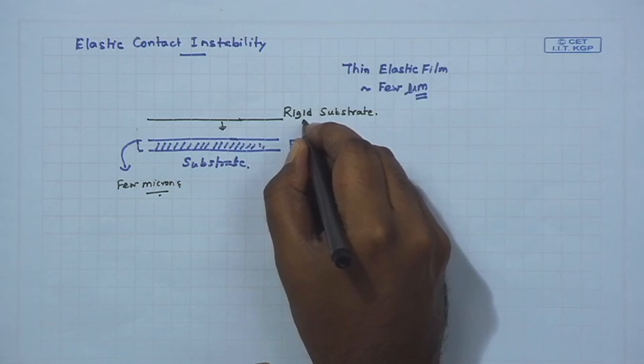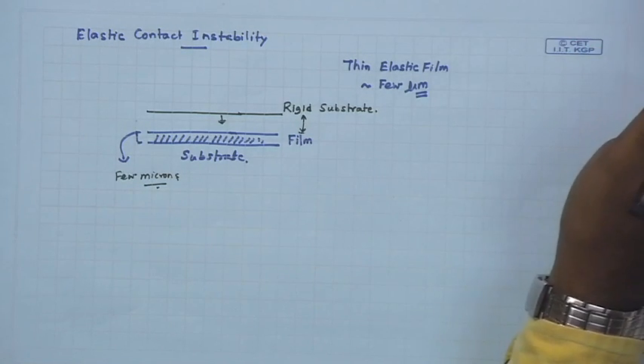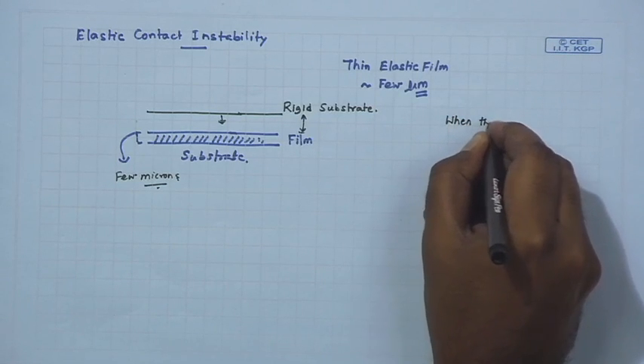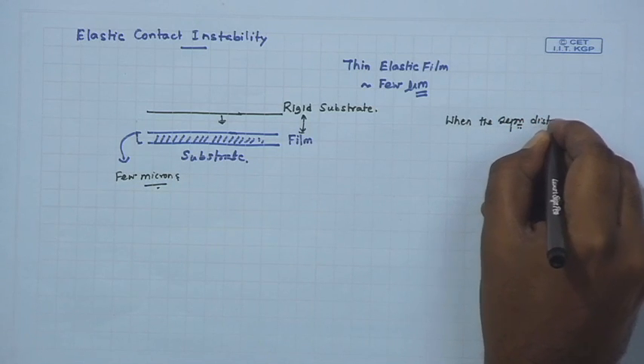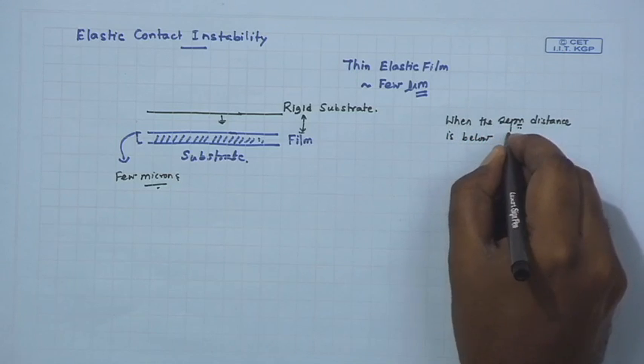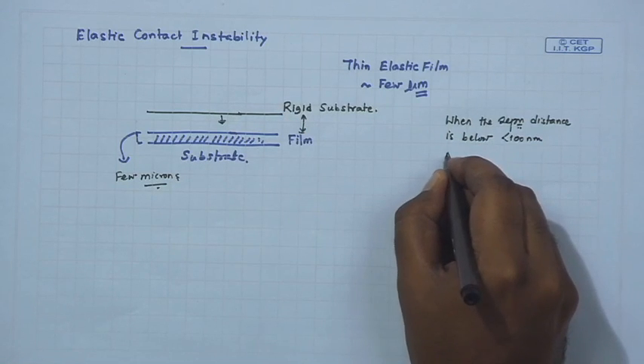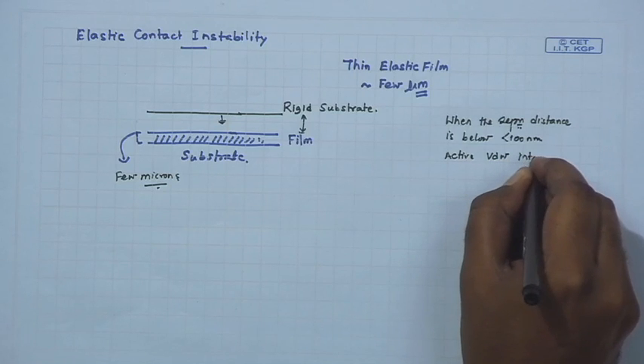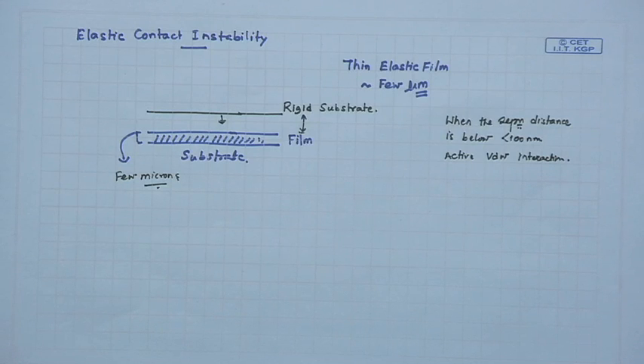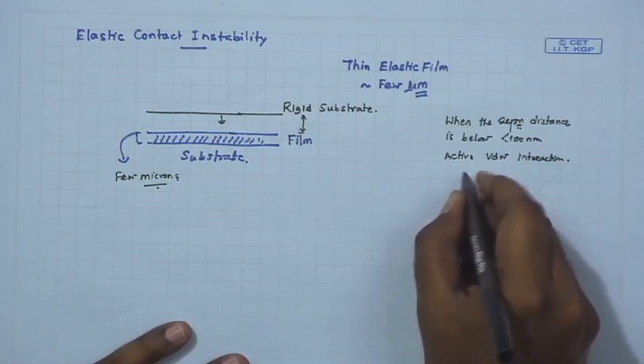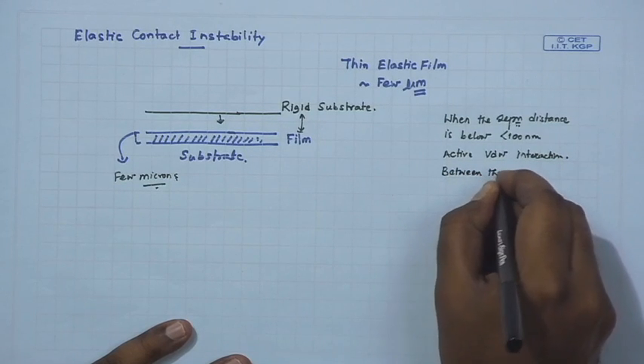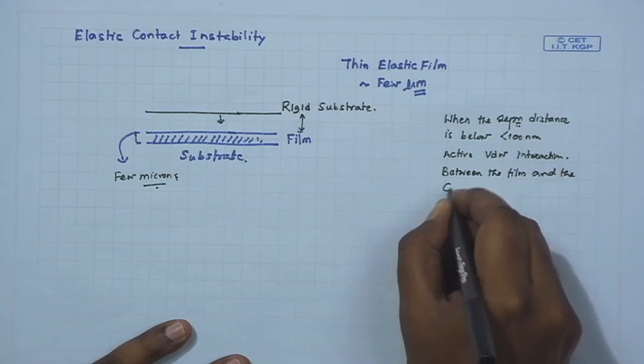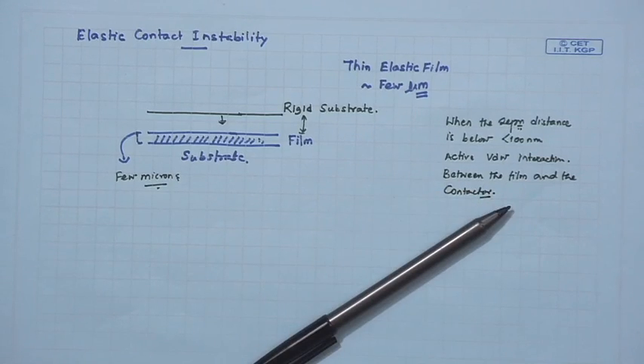But suppose the contactor is close enough to the film and you are bringing it very slowly. Then, when the separation distance is below that critical range of 100 nanometer, there is now active VDW interaction, van der Waals interaction, between the film and the rigid contactor. Just the way in the context of an AFM your tip was chosen to be of a cantilever which is soft enough to deform to van der Waals forces, it turns out that these soft elastic films are also adequately soft and they deform subjected to these van der Waals forces.